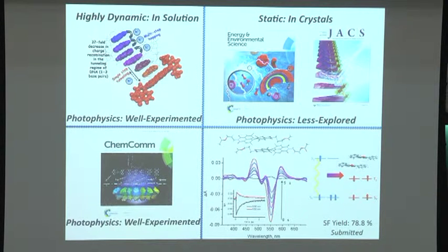And interestingly enough, yet another study that we took up recently is with the perylene diimide chromophore, wherein we put 4 bromo groups on the core position that twist the molecule. Twisting the molecule makes sure that they are not exactly on top of each other, but instead the orbital overlap between these 2 units is very limited, close to 4 to 10%.